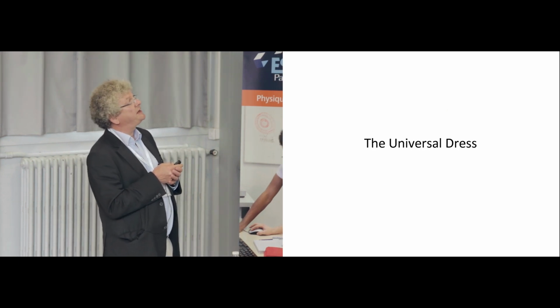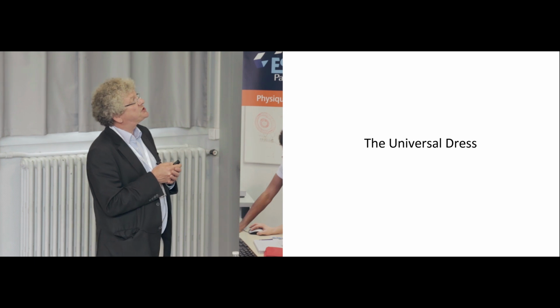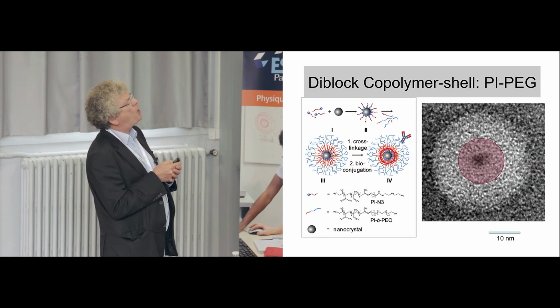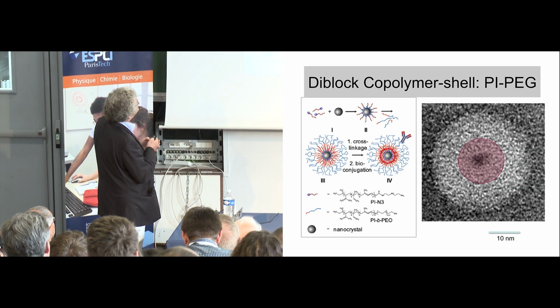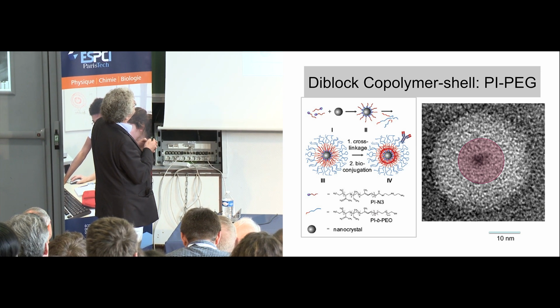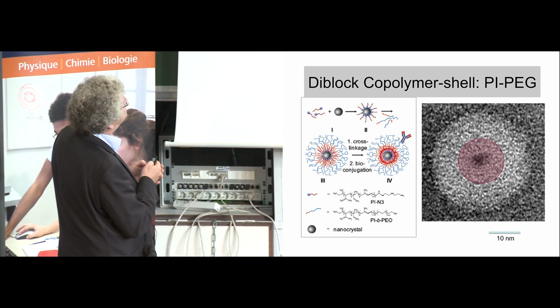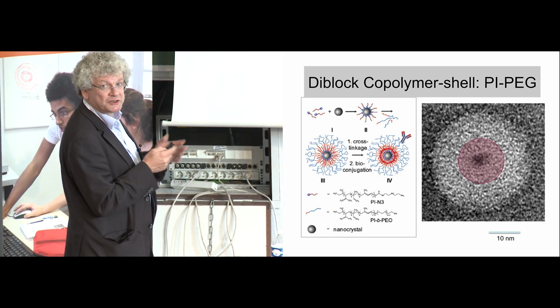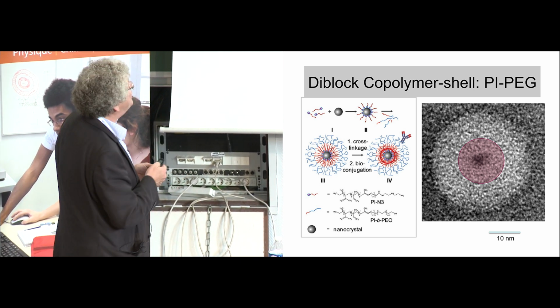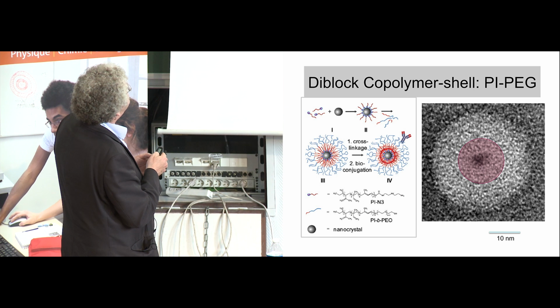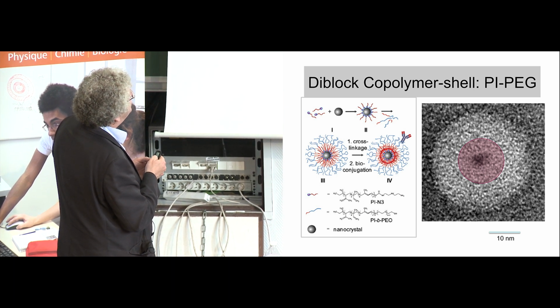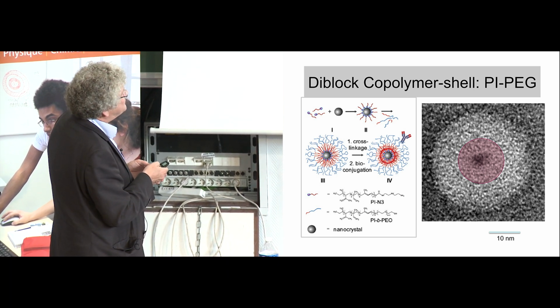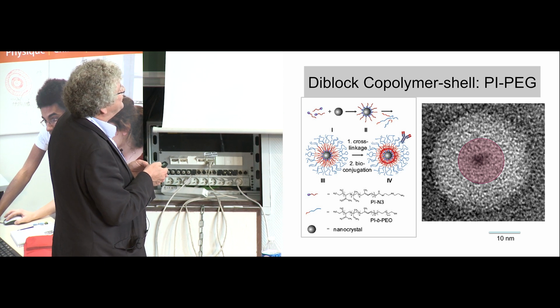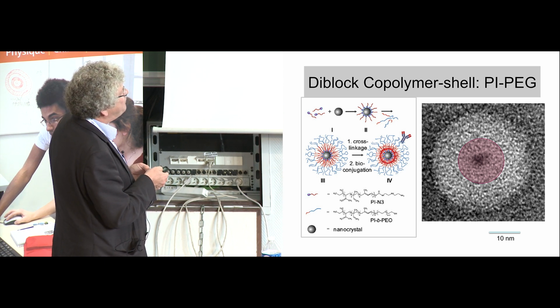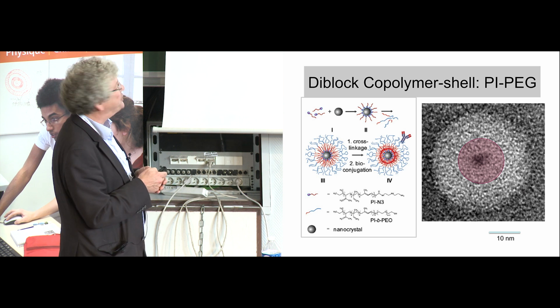And the way we went in Hamburg for that is we take the particles and we first make a ligand exchange, partial ligand exchange against a small oligomer. And this oligomer consists here, this red part is a small polyisoprene chain with something like 2,000, 3,000 molar weight. And here, this binding group consists of 3 amino groups in this case. So a chain with 3 amino groups and polyisoprene.